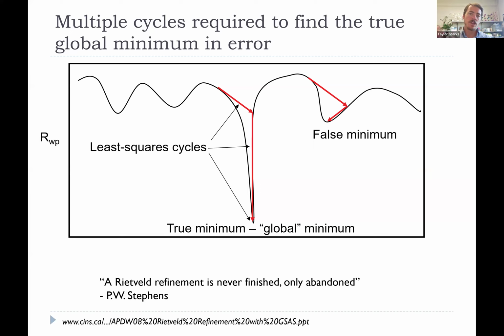Divergence happens when you're changing things and it's not minimizing, it actually starts to increase. That usually is indicative of your structure starting to pick completely silly values that no longer even kind of fit your data. The software is programmed to stop running at that point and go back to the previous non-diverged value. We will probably see some examples of what it looks like when it diverges when we actually try this out today. Okay, so we'll come back to that.